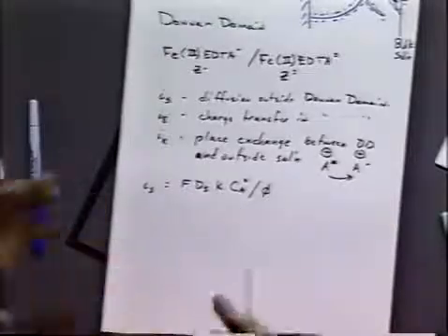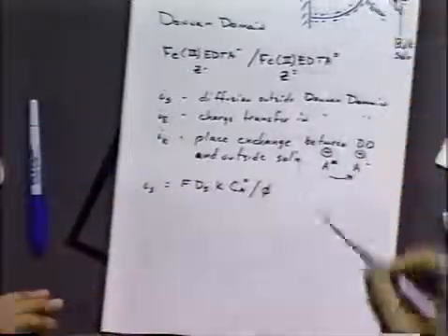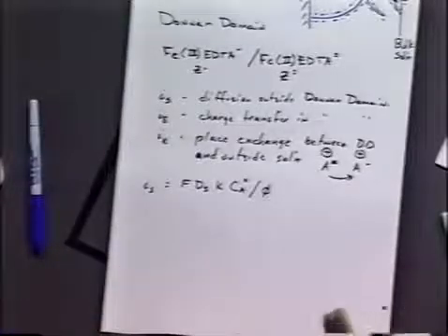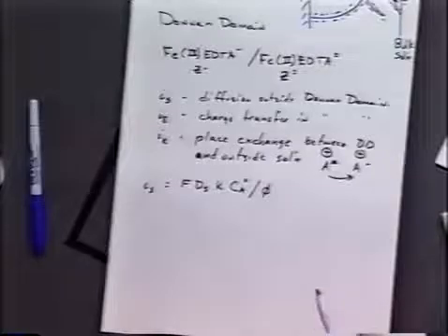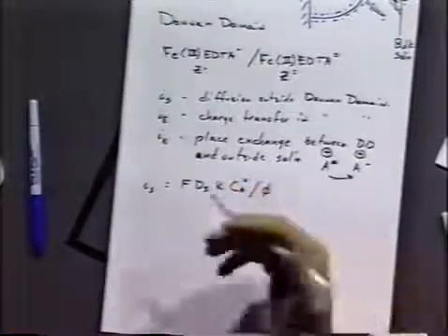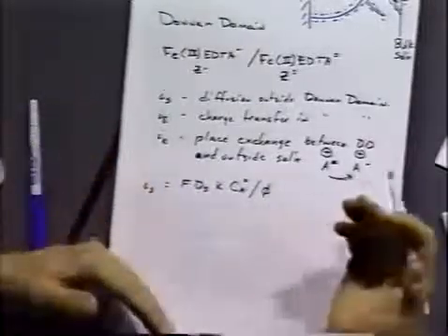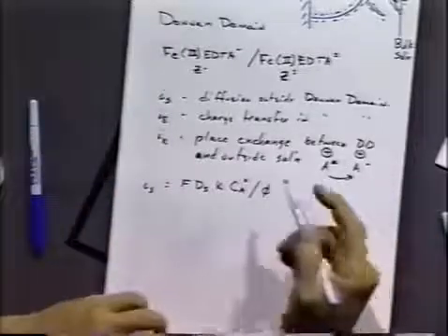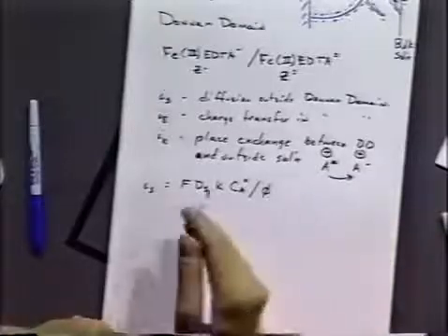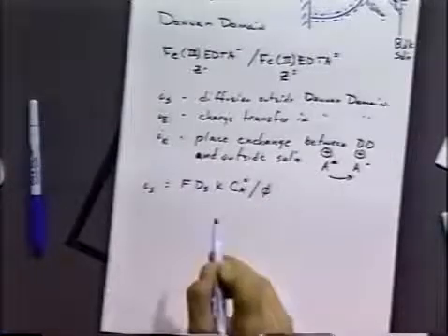So the current in the film that's not in the Donnan domain is going to be related to how thick the film is, obviously, what the concentration is outside the polymer material, what the partition coefficient is, in other words, what's the relationship between the amount of material at equilibrium in the film and in the bulk solution, the concentration ratio, and the diffusion coefficient outside the polymer film. So basically, all these other parts are scaling the diffusion coefficient that way.